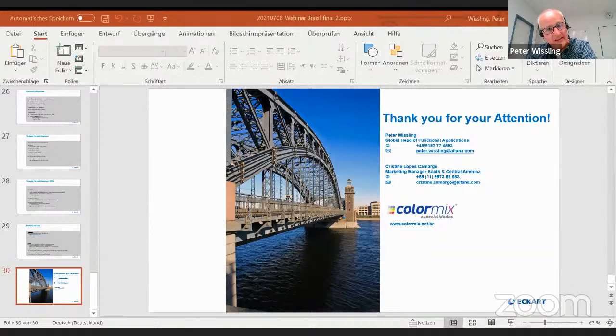We very often find that waterborne systems have a very acidic pH value, pH 4, 5. If you neutralize this to pH 7 and 8, you already can benefit from lower hydrogen gas formation. But in the end, I would also recommend to use a pre-stabilized zinc flake. There are some product offerings available which are already pre-stabilized and suppress the hydrogen gas formation even better.